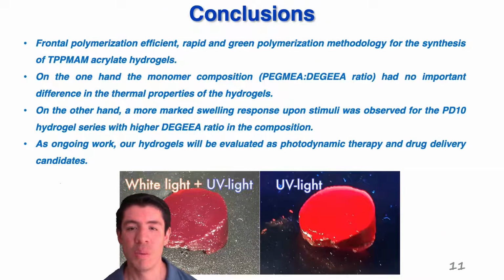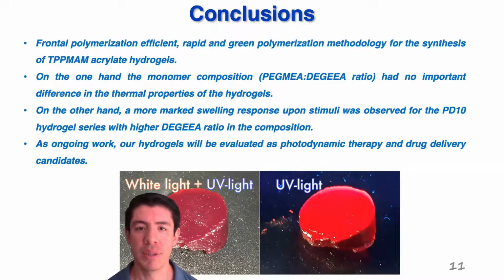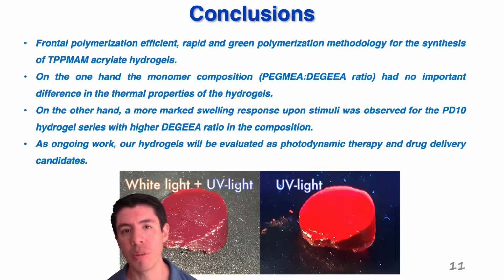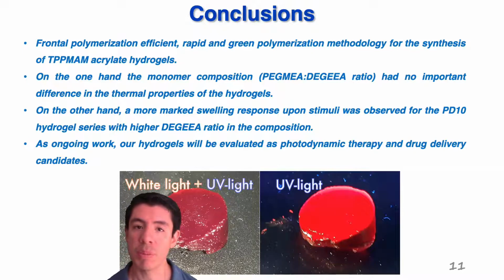In this work, we have used frontal polymerization as an efficient, fast, and green methodology to obtain stimuli-responsive TPP-MAM fluorescent acrylate hydrogels. On the one hand, the monomer composition had no important difference in the thermal properties of the hydrogels. On the other hand, a more marked swelling response upon stimuli was observed for the PD10 hydrogel series, with higher diethylene glycol ethylacrylate ratio. As ongoing work, our hydrogels will be evaluated as photodynamic therapy and drug delivery candidates.